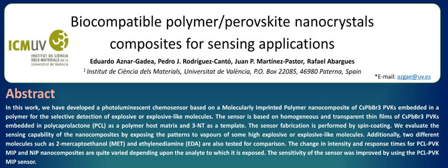In this work, we have developed a photoluminescent chemosensor based on a molecularly imprinted polymer nanocomposite of cesium lead bromide perovskite embedded in a polymer for the selective detection of explosive or explosive-like molecules. Moreover, we synthesize non-molecularly imprinted polymers to compare the results.